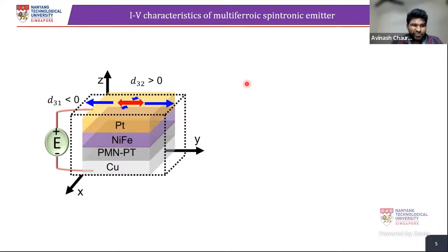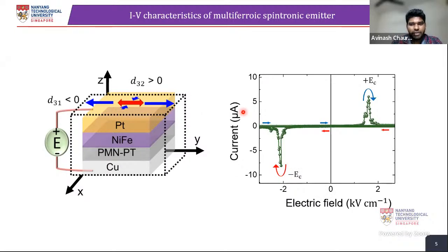In order to do the terahertz measurement, we first do the IV characteristic of the device to find the switching voltages of the PMN-PT layer. These plus E_C and minus E_C are basically the switching voltages on the positive and negative sides. Now we use these switching voltages to apply the sequence and then apply the electric field to see the effect of the voltage on the device.